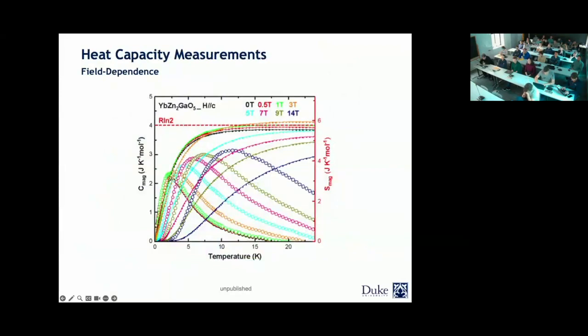So to do that, we actually started to look at the data as a function of magnetic field. So here you're looking at the magnetic specific heat versus temperature. We didn't see anything very surprising, at least within this temperature range. You can see that the Schottky term starts to move up in temperature as a function of field. Again, it saturates at R log 2. So it's all very good.